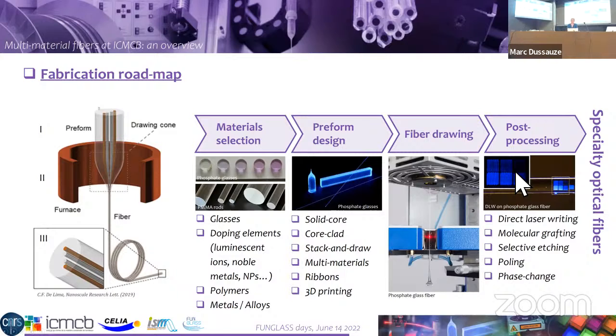The post-processing means, for instance, direct laser writing, as we see as an example on these pictures. On the top right, this is a flat silver photosensitive fiber, made of silver phosphate glass, that has been functionalized using a focused femtosecond laser. On top of that, because we generate a surface, we can functionalize the surface with, for instance, molecular grafting. We can also use a combination of laser inscription and etching to get some topology on the surface of the preform or of the fiber, depending.